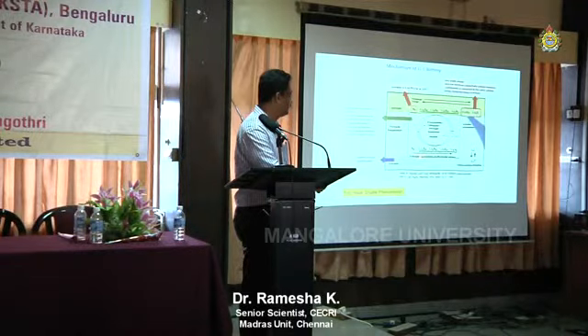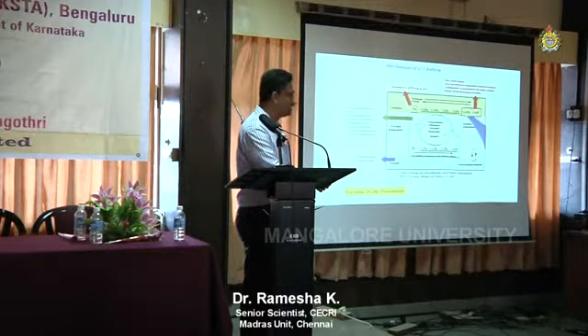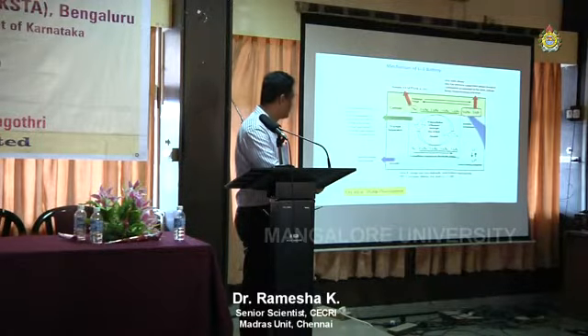But what happens once it dissolves is that it goes to the other side, and forms a solid polysulfide on the lithium side. So the cathode goes and deposits on the anode. That is the problem. The battery will die within a few cycles. That's a real issue. So we come up with a lot of strategies to avoid this polysulfide dissolution, what we also call the shuttling phenomenon, the cathode dissolving and going and depositing on the anode. So we have to come up with a strategy to avoid this.